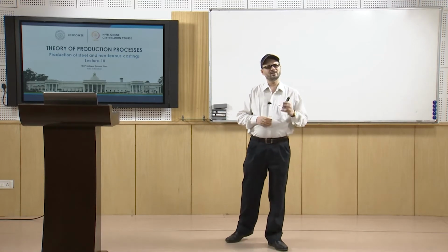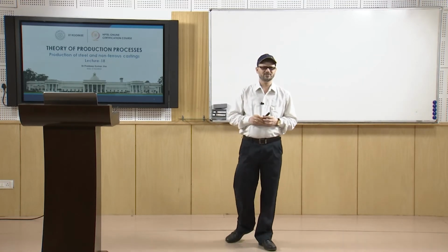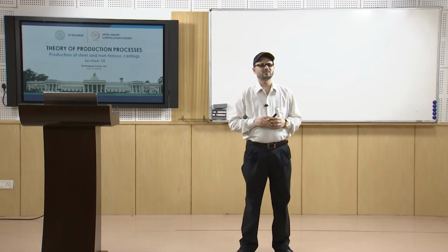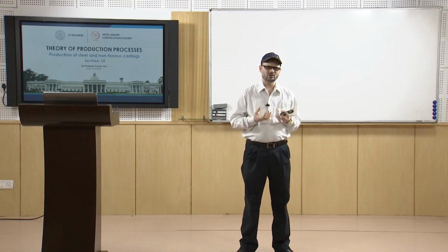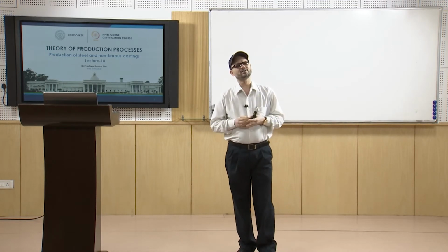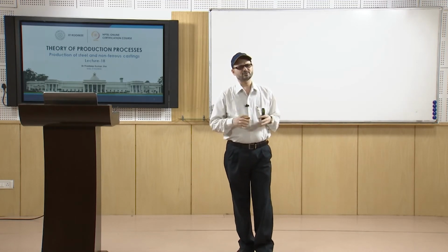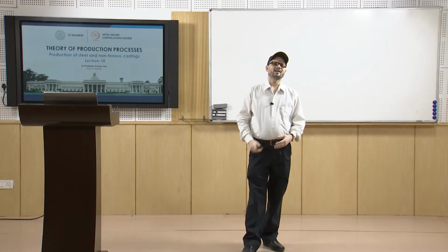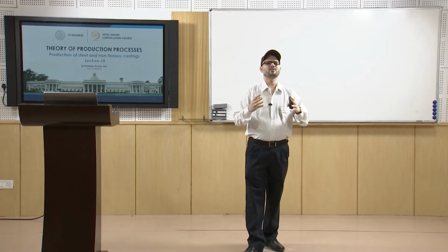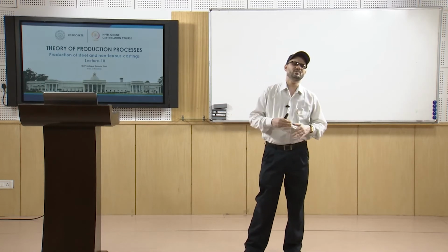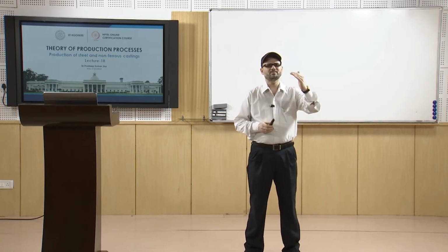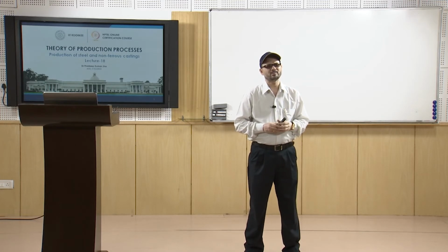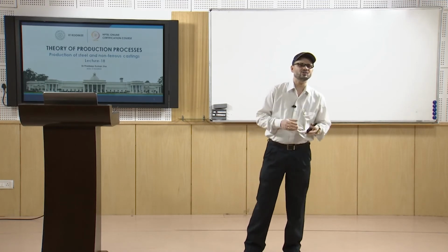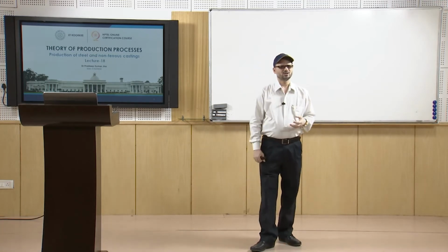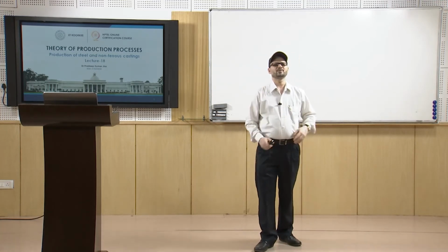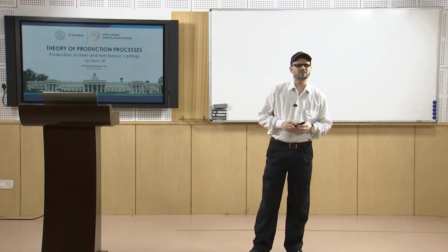Another challenge in the melting practice of non-ferrous materials is loss by vaporization, because these materials are very costly. If you use an improper melting procedure or improper gating or pouring procedure, during the melting itself there may be loss of these precious elements by vaporization. Because the temperature normally is higher many a times, they vaporize and there will be loss of the key alloying elements. That may lead to an improper combination of mechanical properties.